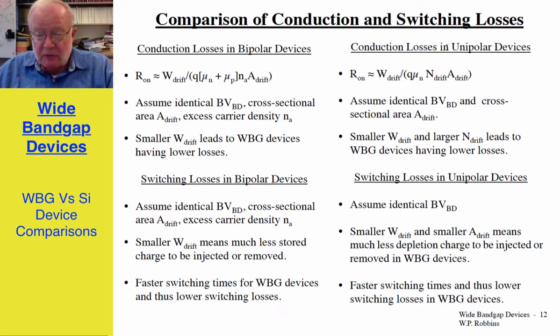Conduction losses in unipolar devices like MOSFETs, again, the smaller drift region length of the wide bandgap device means lower conduction losses. And also, we can have much higher doping levels in the drift region in the wide bandgap device, and that further contributes to lower conduction losses. Switching losses in the unipolar wide bandgap devices, again, are going to be significantly less because of the faster switching times. And that's ultimately traceable to the fact that the device is smaller, particularly the area of the drift region.